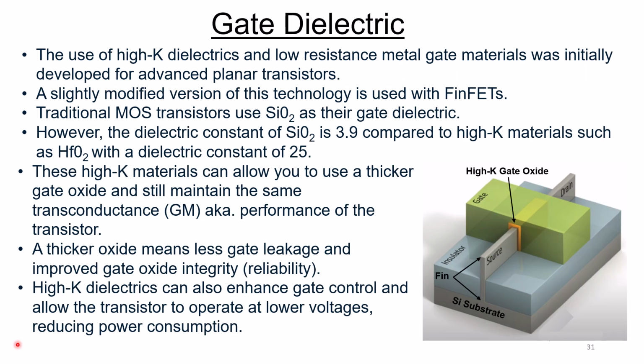The use of high K dielectrics and low resistance metal gate material was initially developed for advanced planar transistors. A slightly modified version of this technology is used with FinFETs. Traditional MOS transistors use silicon dioxide, that's SiO2, as their gate dielectric. However, the dielectric constant of silicon dioxide is 3.9 compared to the high K materials such as hafnium dioxide with a dielectric constant of 25.